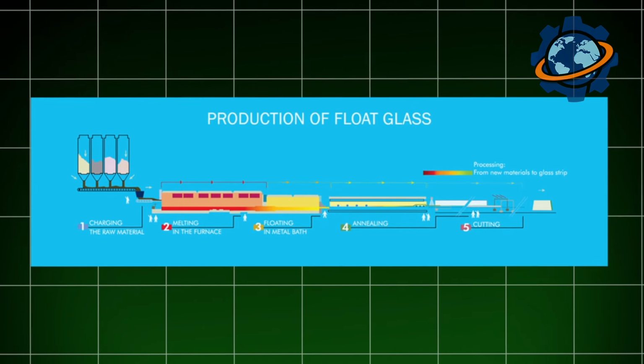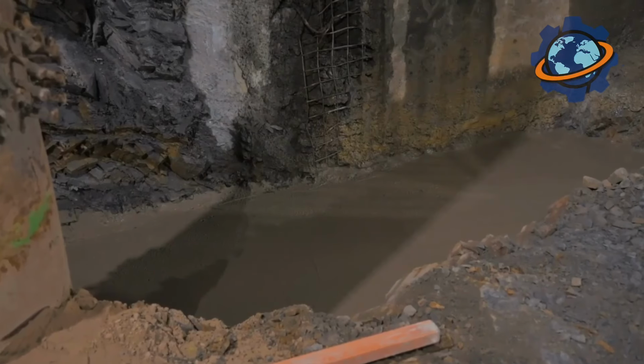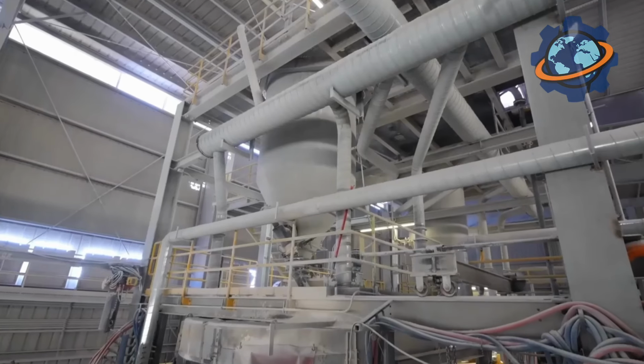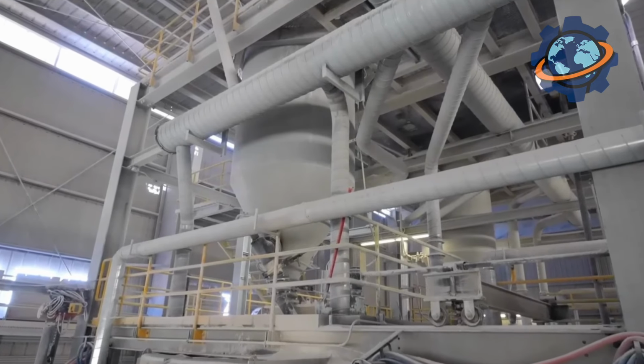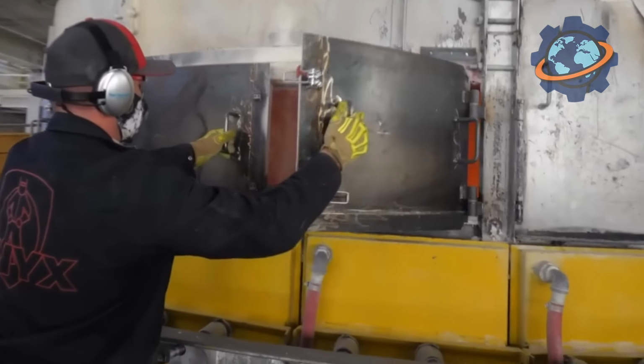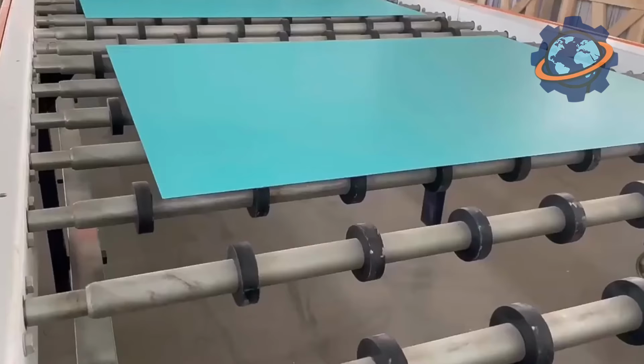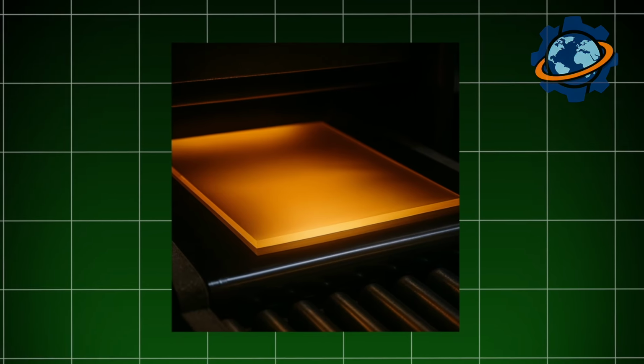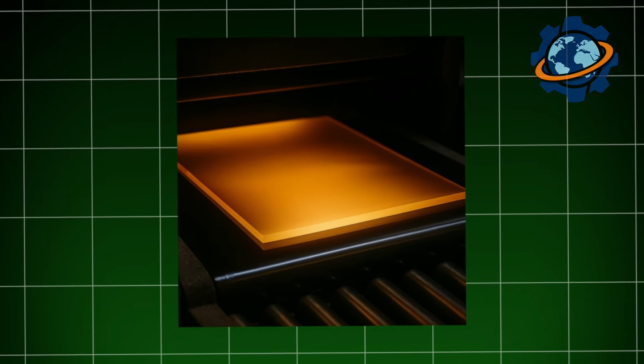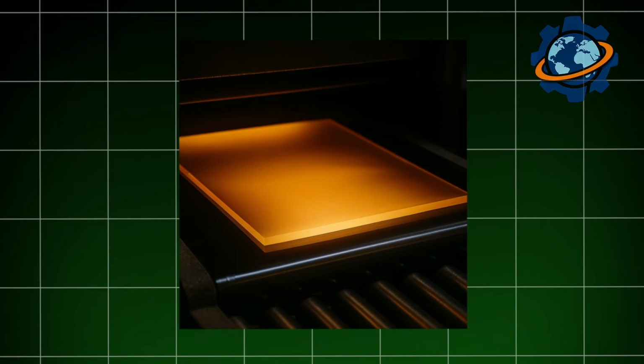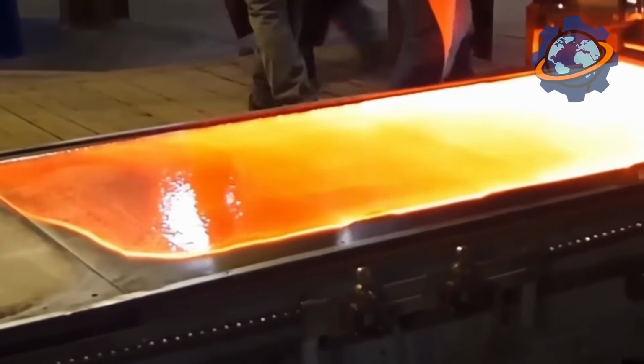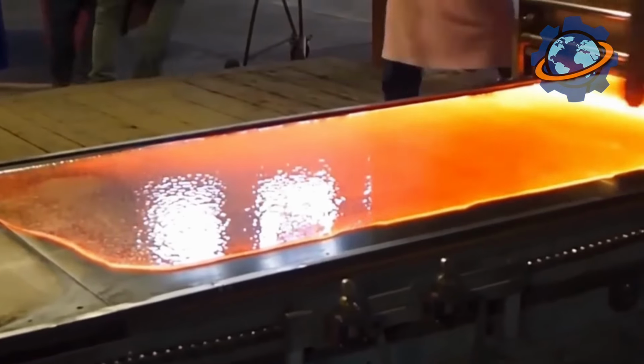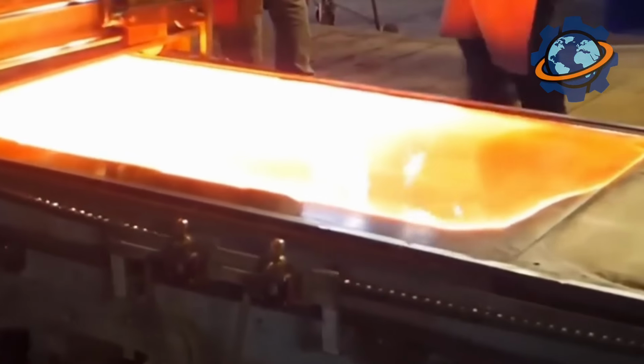The tin bath, stretching for hundreds of feet, has a perfectly smooth, mirror-like surface. Since glass is lighter than tin and doesn't mix with it, it spreads out over the surface, forming a perfectly flat ribbon of uniform thickness. Gravity levels it from the bottom, and surface tension smooths it from the top, creating impeccable optical quality. The speed at which this ribbon is pulled from the bath determines its final thickness with pinpoint accuracy.